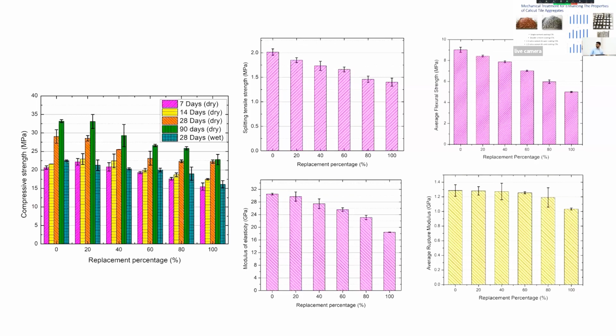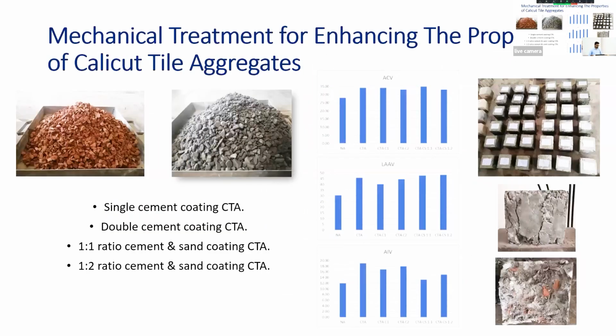For that, they have selected 4 types of treatments, including cement coating and cement sand coating. The second figure shows the treated Calicut tile aggregates. Appearance-wise, it's almost like normal aggregates. They have done the testing for the aggregates and observed positive improvements in the aggregate properties. In addition to that, now they are at the stage of investigating the properties of concrete with these treated Calicut tile aggregates.